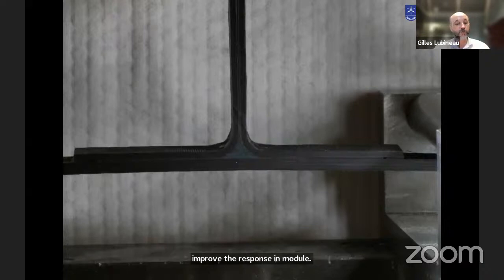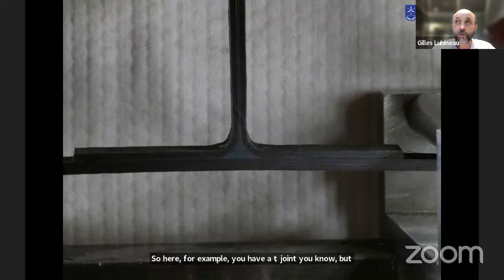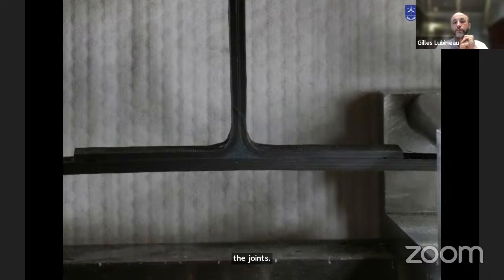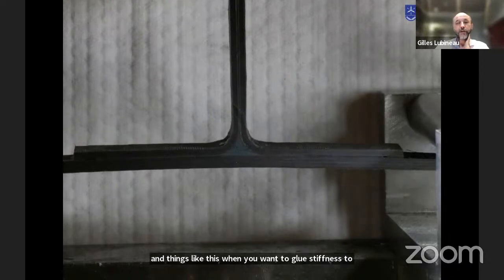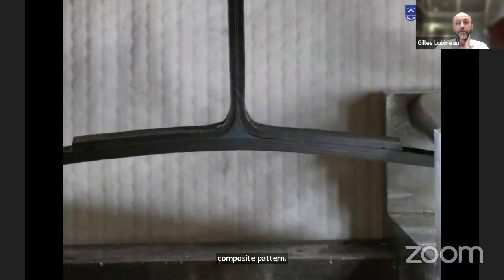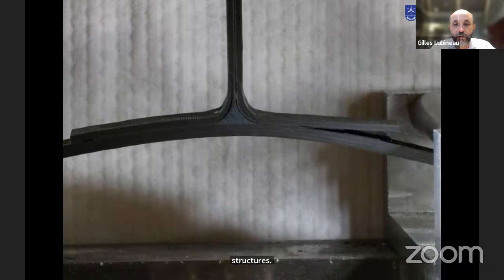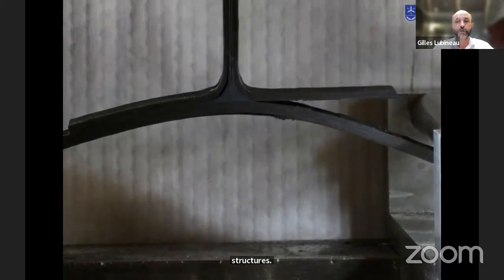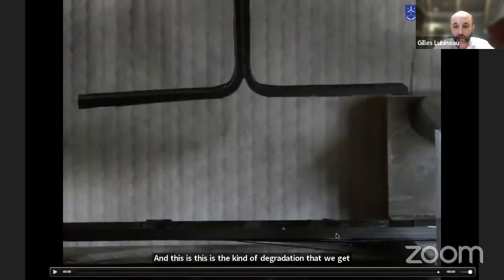So what I would like to show you now is how you can use this for real applications. So here, for example, you have a T-joint. You know that the T-joint is a very classical structure when you go to stiffeners and things like this, when you want to glue stiffeners to a composite panel. This is something that is really interesting in terms of structures. And this is the kind of degradation that we get when we are using our surface treatment. So what we do here is that instead of gluing the T-joint directly to the composite substrate, we modify